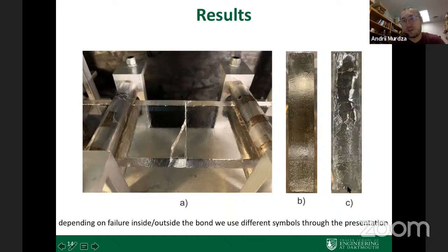And then on image C, you can see the bottom part of the sample, where the fracture was along the bond. You see a kind of rough surface. And on the upper part, we can see the clear newly formed fracture in the new ice, not along the bond. And for all my results, in case the failure occurred outside the bond, I would use triangles, different symbols. But in most saline ice samples, as I mentioned, the failure was along the bond.